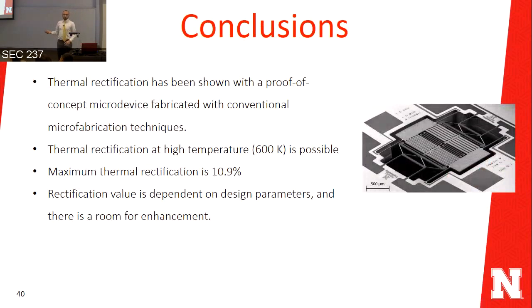So what we take out of this research is that thermal rectification is possible practically, experimentally at high temperatures. We have achieved thermal rectification at 600 kelvins, and the maximum rectification was 10.9%. It's kind of not impressive, not very high, but we have chance for improvement. And the rectification is dependent on design parameters. So if we spend more time optimizing the design here, we can achieve higher thermal rectification.